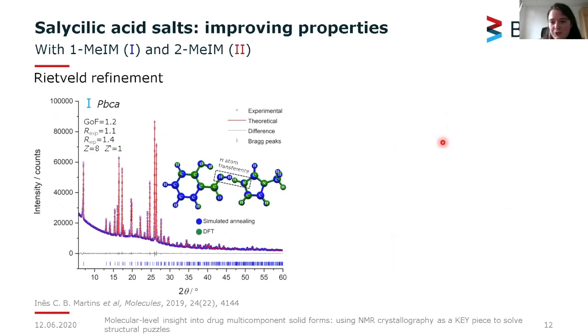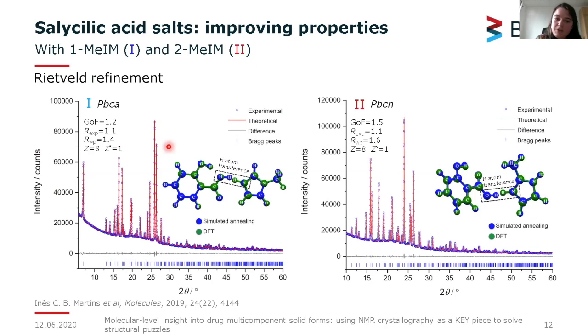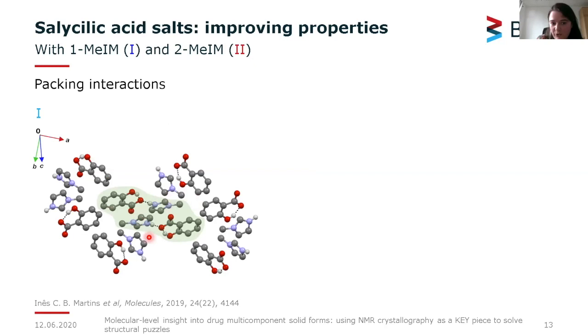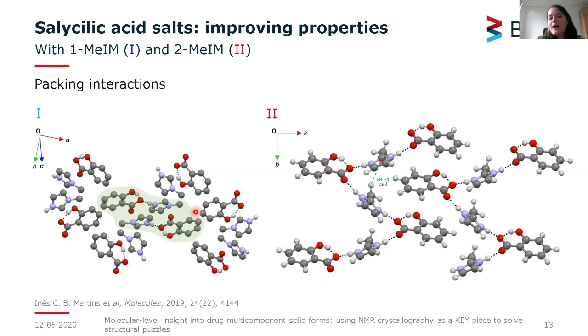For the other two examples with 1-methylimidazole and 2-methylimidazole co-formers, we applied the same approach — solving the structure by powder X-ray diffraction and performing geometry optimization with DFT. We observe the same behavior: a transfer of the hydrogen atom indicating salt formation. The packing structures are somewhat different. For 1-methylimidazolium, the aromatic methyl group blocks one nitrogen position, so it is not involved in hydrogen bond interactions, giving a sandwich-type packing structure. For 2-methylimidazolium, we have a zigzag packing structure with C–H···π interactions between the imidazole molecules.